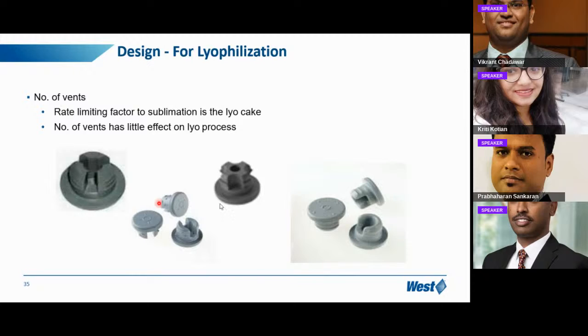We have internal as well as external studies in both cases. The impact of one, two, or three legs will be the same. So the number of legs, number of vents, is not an important factor when considering lyophilized versions.